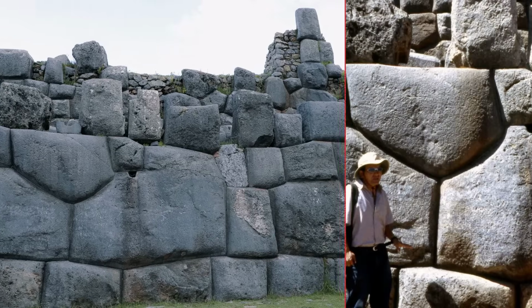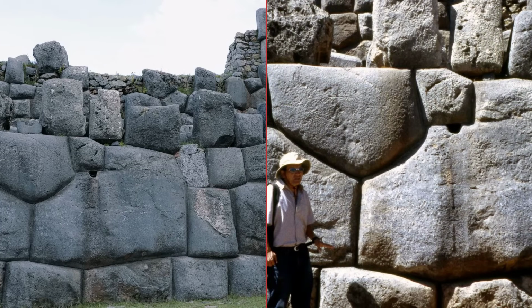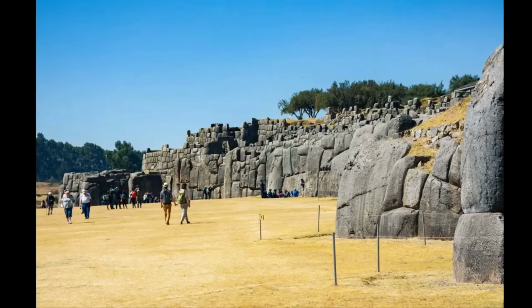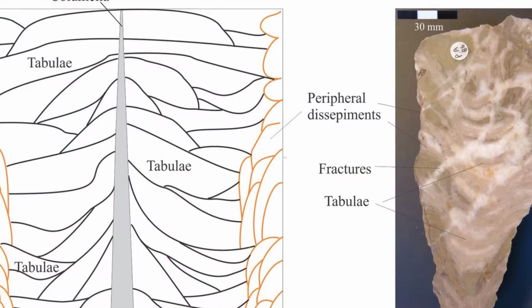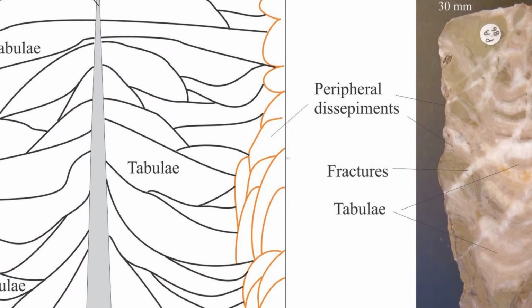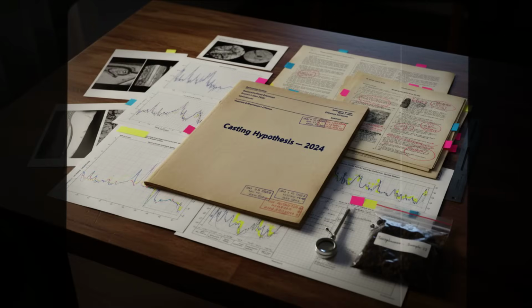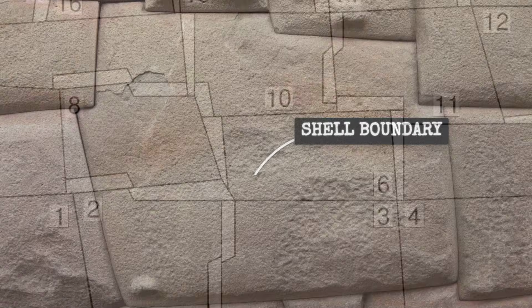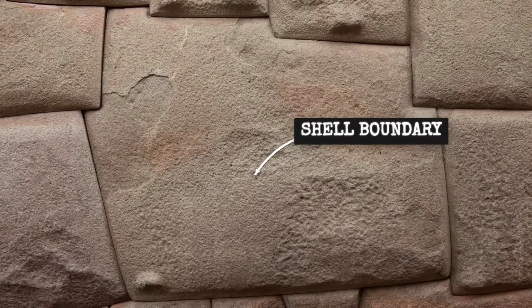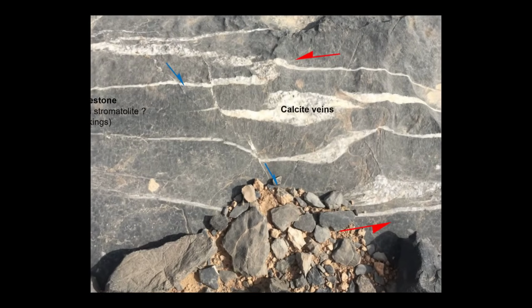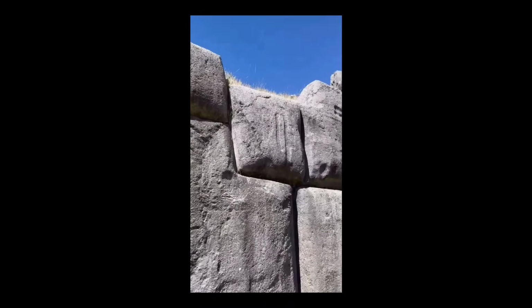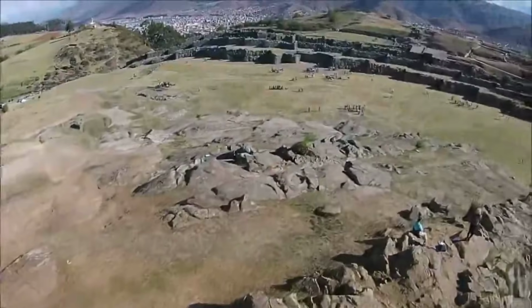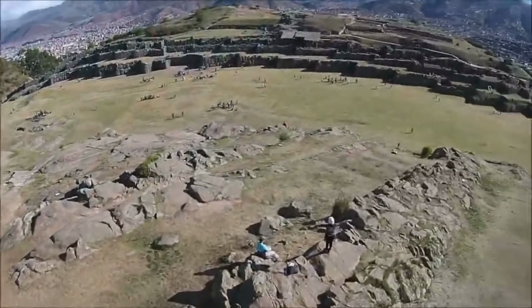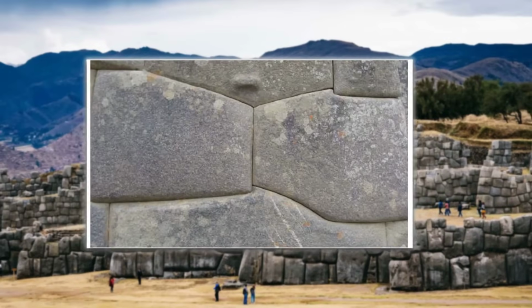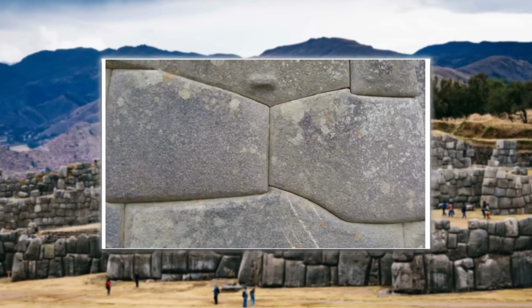The distinction between so-called Type A and Type B blocks became a focal point. Type A stones, mainly at the wall's base, sometimes displayed a denser outer shell over a slightly coarser core. Early interpretations hinted at artificial agglomeration, a shell cast over fill material. Yet the shell's boundary was gradual, not sharp. Natural mineral veins cut through both shell and core, undermining the idea of separate casting phases. Type B blocks, forming the upper courses, were uniformly microcrystalline throughout, indistinguishable from unworked outcrops on the hill.